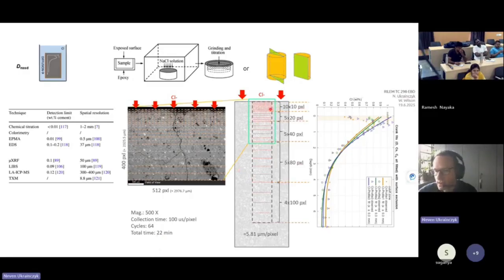And then later, when we analyze this data, we are doing the smaller areas where we collect the chemical composition. So it takes the statistical average chemical composition of each of these windows. And this is then per depth. At the beginning, we take more points because it's more interesting, and later there is a constant value, so we can take bigger areas.